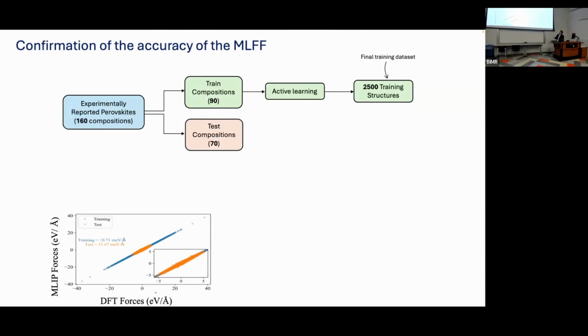We could calculate its energy, both in terms of the training test set. You can see here that these values are in the meV per angstrom. So they're very, very accurate for forces. And that's really the key thing. For stable MD trajectories, you want very, very accurate forces for your ML potential.